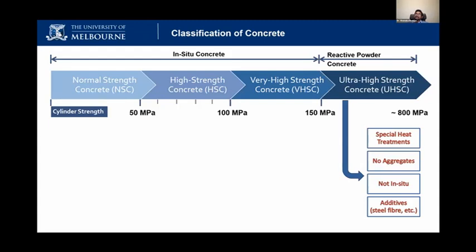So this ultra high strength concrete, the reactive powder concrete, is basically a powder. It's only a powder. There are no aggregates there. So it can even achieve 800 megapascal using a special curing method. Researchers have even achieved 800 megapascal. So that's where we can go. However, the cost is the problem. The cost is really high because it purely consists of binder, and also includes expensive additives such as silica fumes and a lot of cement. So that's why reactive powder concrete is not very popular in in-situ construction and also in buildings. But in Japan, they have used reactive powder concrete for taller building applications. But cost is the main problem.